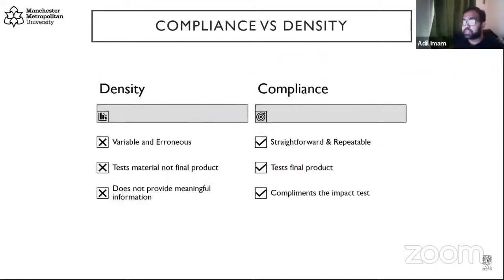Our findings from this study showed that density as a regulatory material property is quite variable or erroneous. You only test the material, not the final product, and usually our foams are stuck between two layers of fabric and it does not provide any meaningful information. Whereas compliance, on the other hand, is quite straightforward. You can write a program on a universal test machine and it would do the test for you. You test the final product, the material and the fabric in combination as to what a player would wear during the game, and it complements the impact testing. So one is a low speed compression test, one is a high speed impact test. So we published this and it is an open access paper in the sports engineering conference.